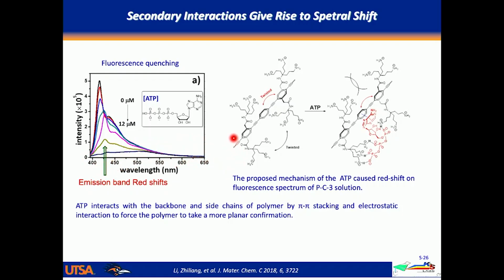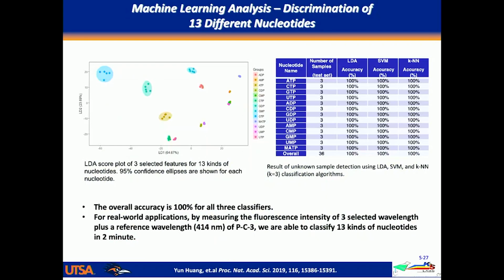This is a cartoon. It's not supported by any real data, but we think that there are specific interactions taking place at the molecular level that have an effect on the conformation of the backbone, and that's possibly what gives rise to these shifts in the spectra. But what's useful in this case is that there is a shift, and it's reproducible, and it depends on which phosphate we use. And so that's a basis for using machine learning or training to build a sensor.